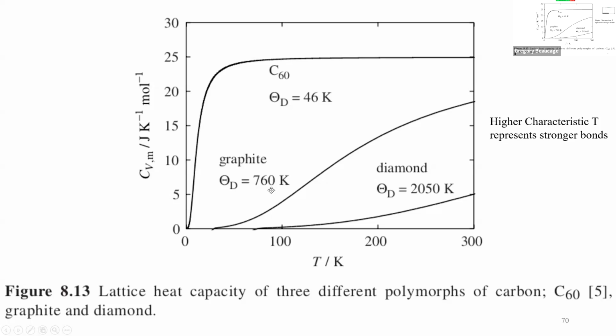All right, and then it asks about if you raise the temperature to 1,000 degrees, the diamond heat capacity becomes larger than the graphite at like 1,000 degrees or something. Anyway, that's in the homework this week, but it's showing that the strength of the bonds between the atoms decides the temperature dependence of the heat capacity, and also the 3D arrangement. So if you reduce these by the Debye temperature, the curves kind of fall on each other.